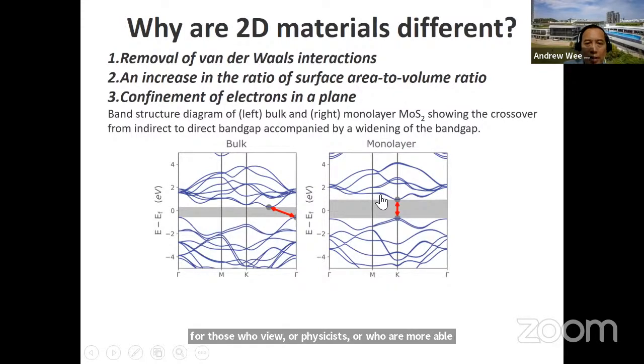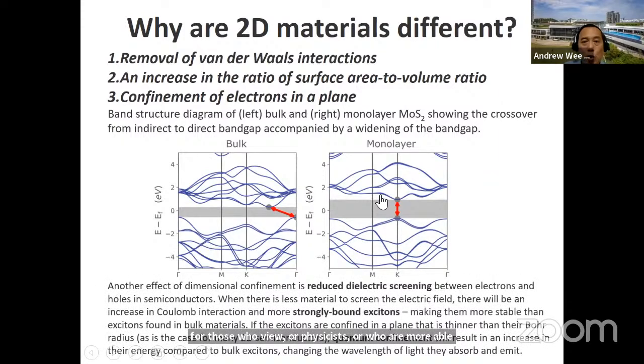So perhaps in more physics language, for those of you who are physicists or who are more able to understand it in physics terms, you can say that the effect of dimensional confinement is due to reduced dielectric screening between the electrons and holes in the semiconductors, because there's less material now to screen the electric field. There will be an increase in Coulomb interaction and more strongly bound excitons than those found in bulk materials. And these excitons are confined in a plane that's thinner than the Bohr radius. And because of that, you get a quantum confinement effect.